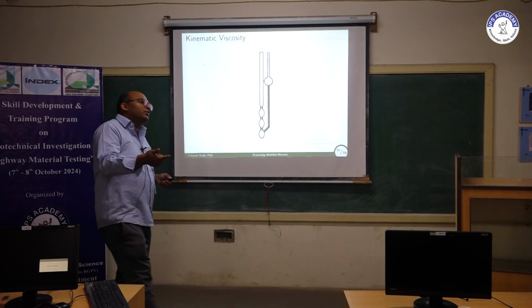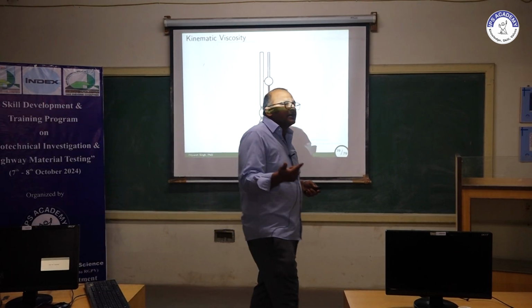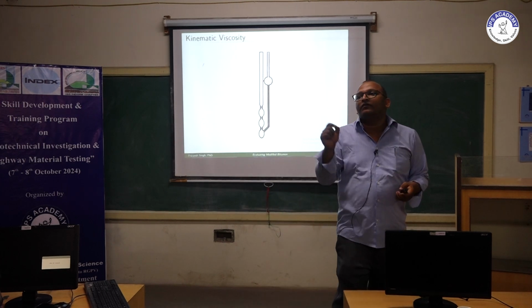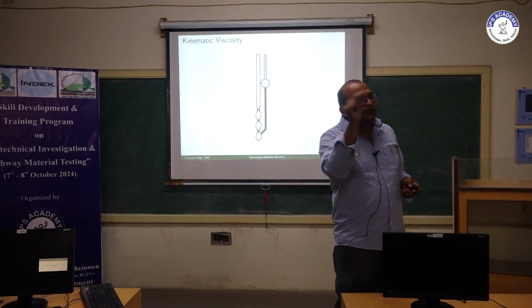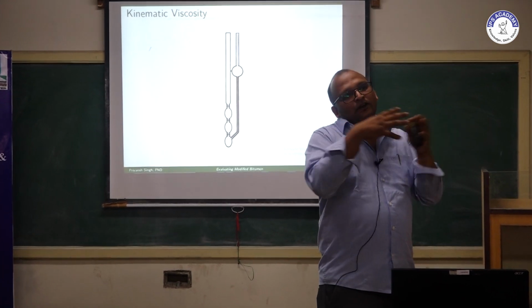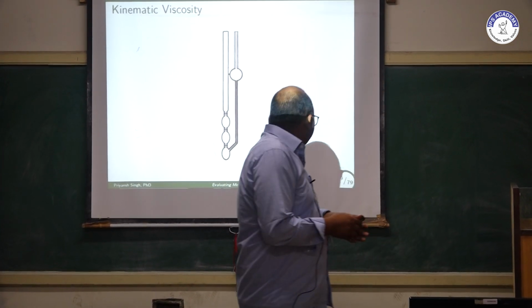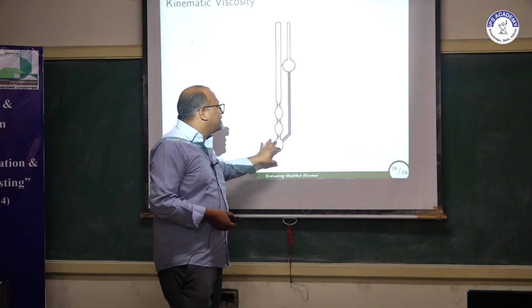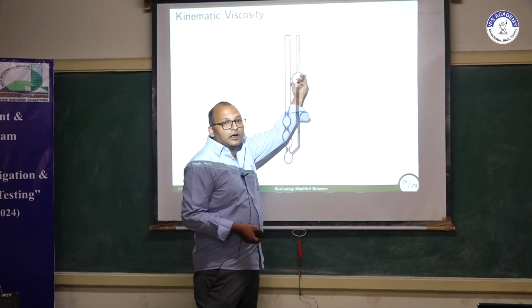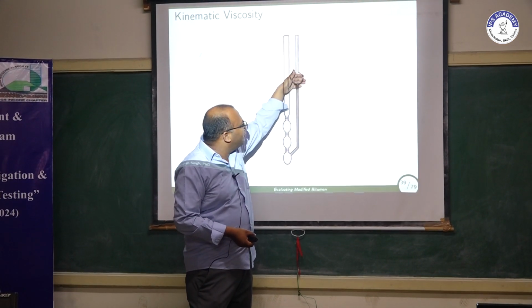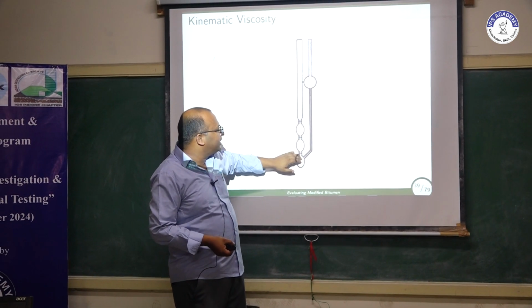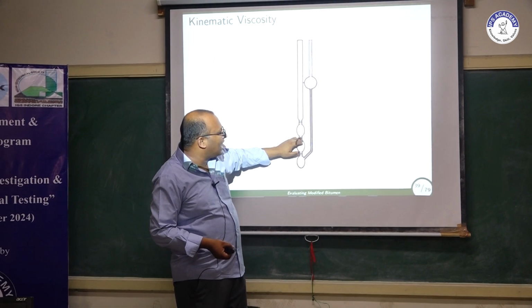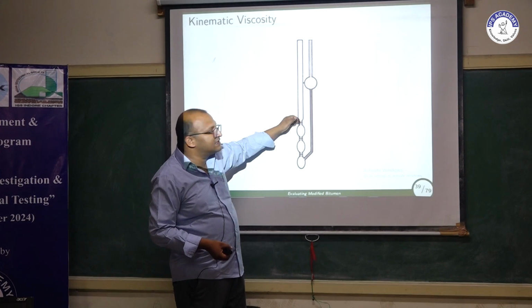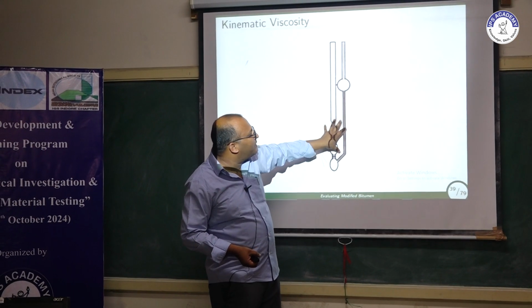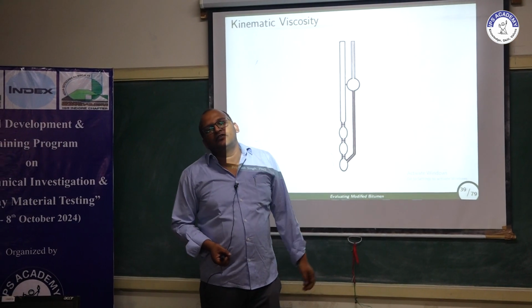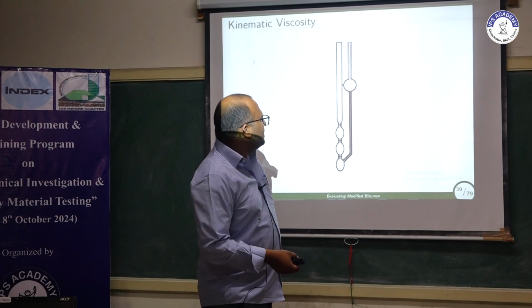Then one more test we do for viscosity is kinematic viscosity, and that we actually do at 135 degrees Celsius, and that is to signify the mixing and compaction. For that we normally use a Cannon Fenske tube. Here we will load our binder in this bulb, and then we will allow it to cross through these lines, and we will note the time when the binder crosses these lines. Again, that time multiplied by this tube's constant will give you the kinematic viscosity of the material.